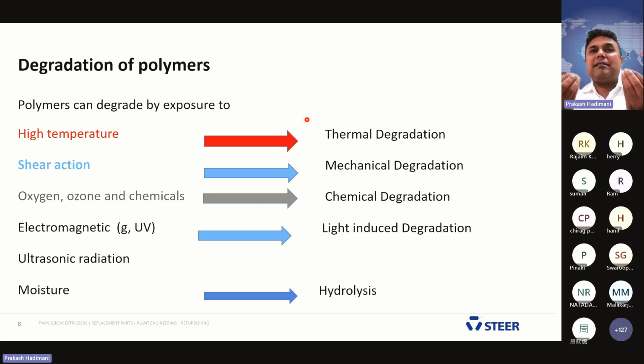What are the behavior changes when you apply higher temperature inside the vessel? When you increase the heating, thermal degradation happens on the polymer. Second, shearing action. If you apply more shear or a harder screw design, the polymer behavior changes. Mechanical degradation means it loses its molecular weight; it breaks into smaller and smaller pieces. If you use a hardened screw design and higher RPM, sometimes more than 1200 RPM or less than 500 RPM, depending on the application, this shearing action we call mechanical degradation.